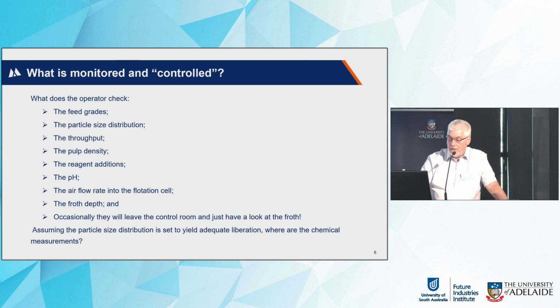He'll rely on somebody out in the field to do some of these readings. But as we know, flotation is about the hydrophobicity of the surfaces of the particles we're trying to separate. There is no measure in there of hydrophobicity. There's no chemistry measured in a flotation plant which is relying on the modification of the surface chemistry in the process.